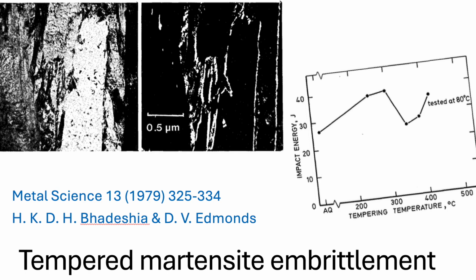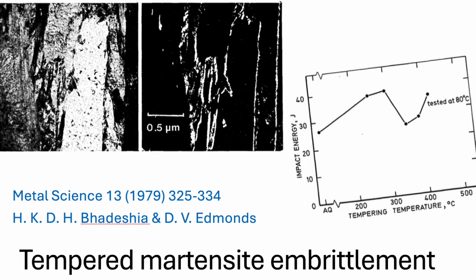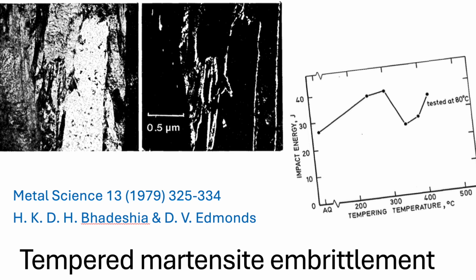Exactly. It's a very planar, highly brittle failure mode with very little energy absorption, very little plastic deformation before it snaps. And the key observation was this. When they looked closely at the fracture surface using microscopy, both the main primary crack path and the internal secondary cracks that formed ran almost perfectly parallel to the direction of those original martensite laths. Wow. So the crack isn't just wandering randomly through the material. Not at all. It is specifically following the structural lines defined by those laths, where the cementite films are.